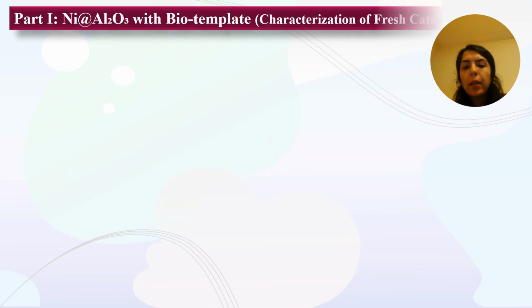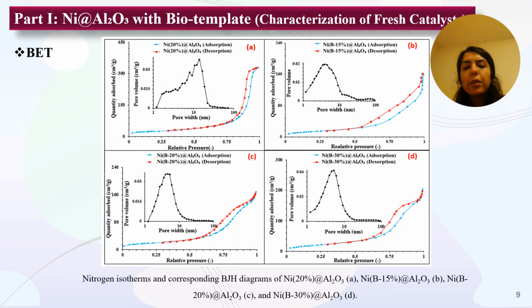In this slide, you can see the BET result, which was so important because it showed the effect of biotemplate on the porosity. As you can see, we had a wide range of pore distribution for the sample without biotemplate. But for the samples with biotemplate, we had a narrow pore distribution, which showed the effect of biotemplate on the catalyst.